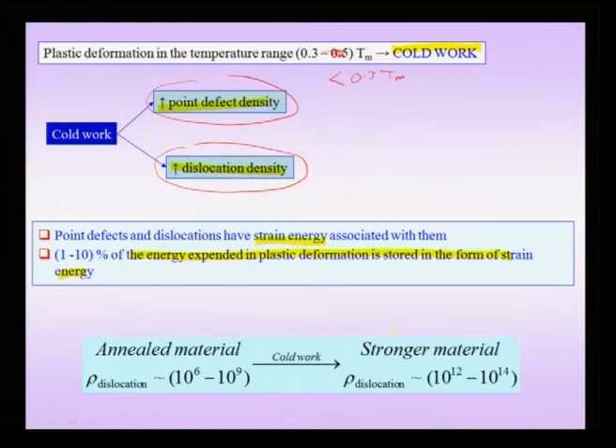Now suppose I have a well annealed polycrystalline material, like copper or aluminum. The dislocation density is of the order of about 10^6 to 10^9, and when you do cold working of this material, not only does the material become stronger because of this cold work, but the dislocation density increases to about 10^12 to 10^14. In fact, it is the increase in dislocation density which is causing the increase in strength of the material. So there is a few orders of magnitude increase in dislocation density, and these strain fields of the dislocations store energy, about 1/10 or about 1/100th of the energy expended in cold work is stored as strain energy within the material.